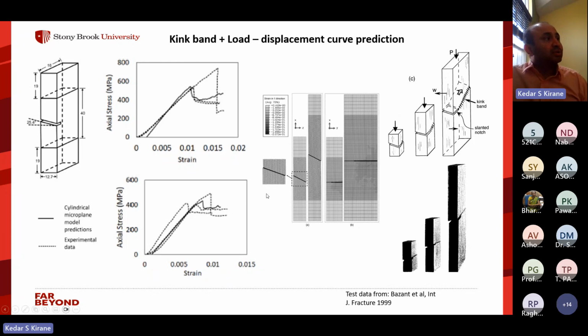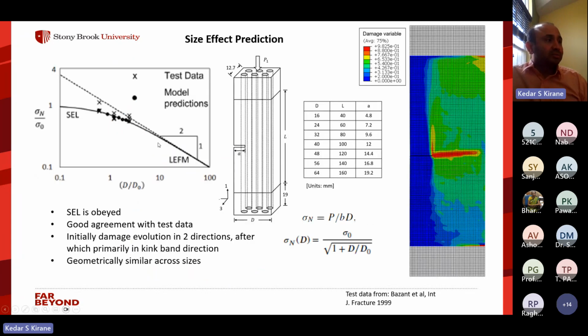And going back to the size effect, which I mentioned, actually the experiments had shown that even this compressive failure shows the type 2 size effect type behavior. And actually we simulated it, and you can see that the model also predicts it. So for sure, this is the quasi-brittle failure mode. And if you calculate the fracture toughness from one particular size, it is going to be size dependent. So even for kink band formation, this size effect is going to be very important.